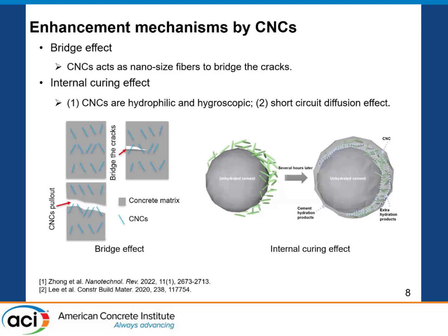And also, as the CNCs are highly hydrophilic and hygroscopic, they could be used as internal curing agents, or have an internal curing effect that can promote some of the hydration and also supply some of the water during the hydration, which can help reduce the shrinkage.